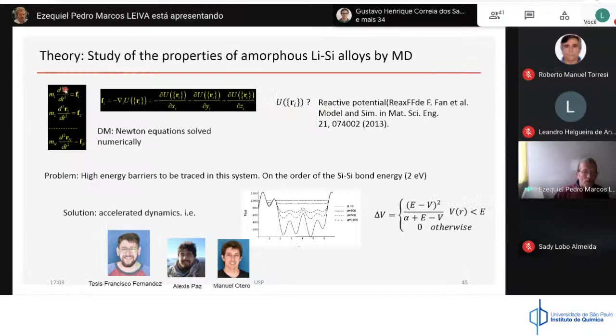Molecular dynamics is very simple. It's a very simple thing you can do with the computer. You just solve Newton's equation numerically, that is, the force is the mass times the acceleration. To integrate this equation you need the forces, and you get the forces as minus the gradient of some potential energy. This potential energy must come from some reasonable assumption, and in this case, we took a reactive potential. The reactive potential is not quantum mechanical, but it gives you an idea of the interaction between the particles of the system.